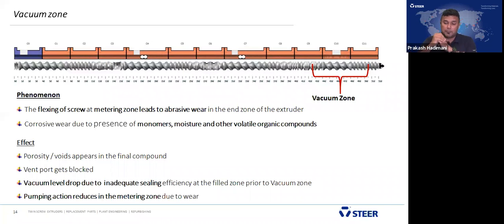Porosity. For example, if the vacuum didn't function or stops, then what effects happen? The effect is porosity and voids in the final product, which lowers the mechanical property, and that appears in the final compound for many reasons. When the port gets blocked, because wear and tear takes place in that particular section, the vent starts flooding and blocks the complete zone. Vacuum level drops due to inadequate sealing, the efficiency at the filled zone prior to the vacuum zone, and the pumping action reduces in the metering zone.